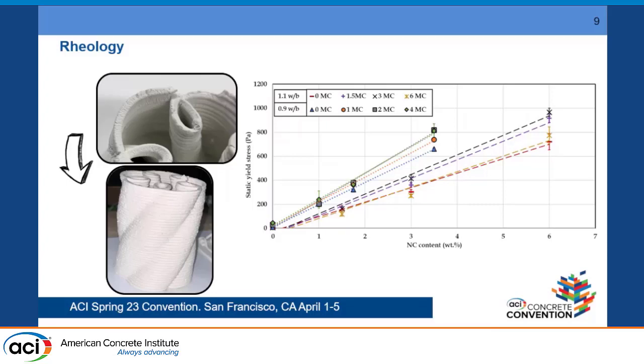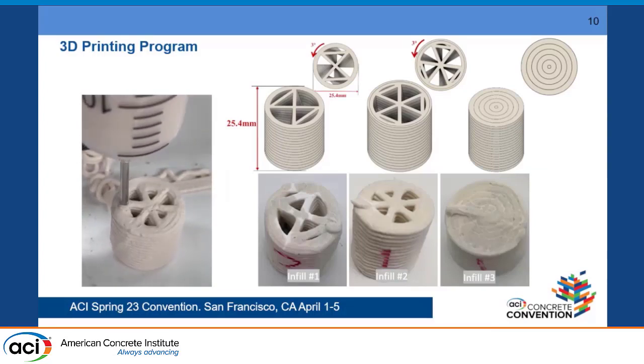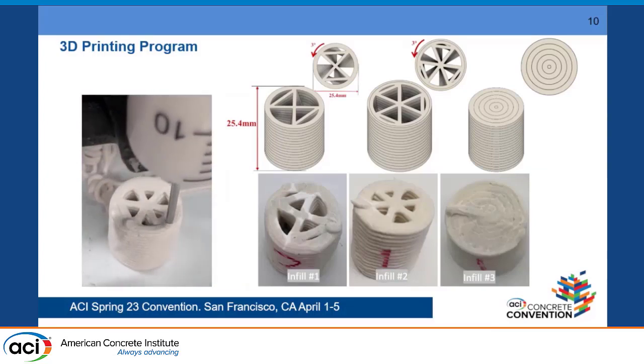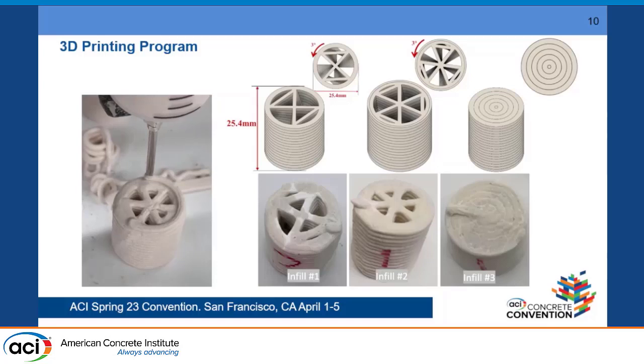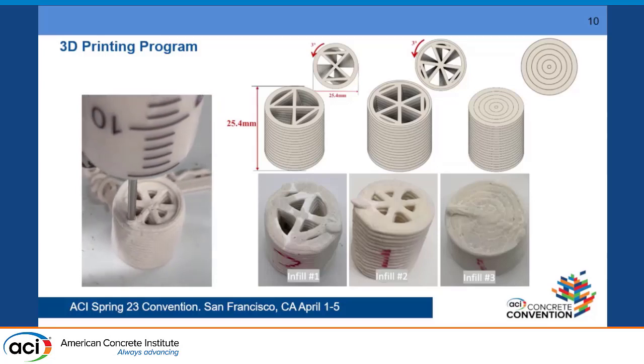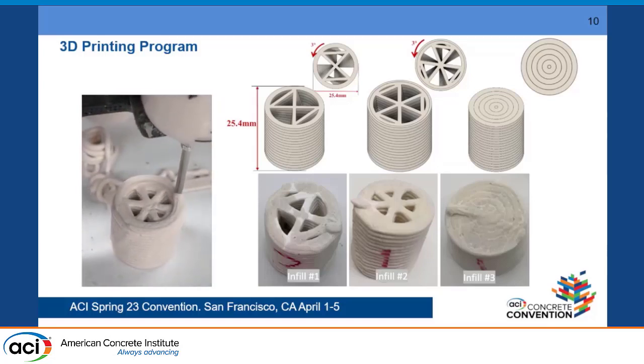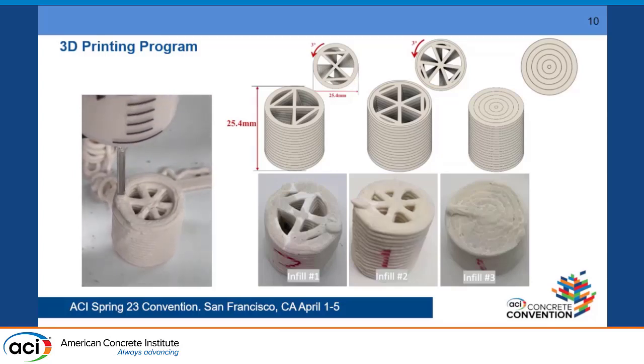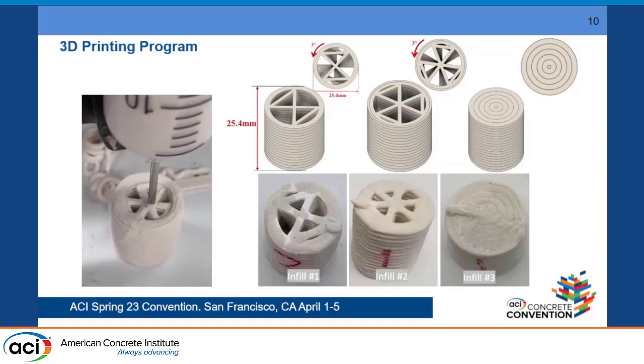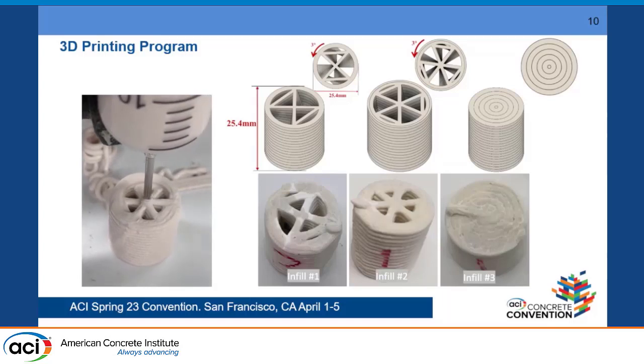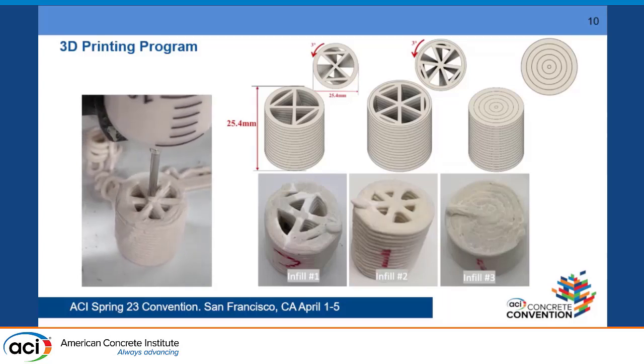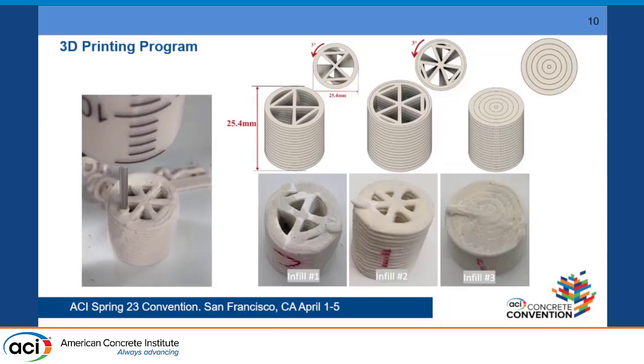So when I was able to 3D print the material, I created an experimental program looking at 3 different infill patterns. This is a video of how the second infill pattern is being printed. You can see here 2 open, internally structured infill patterns of small specimens, and then a third one which is closed, and this is meant to mimic a cast specimen, just to isolate what changes are happening because this material is being 3D printed.